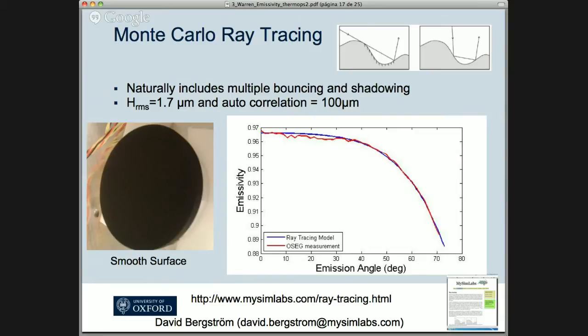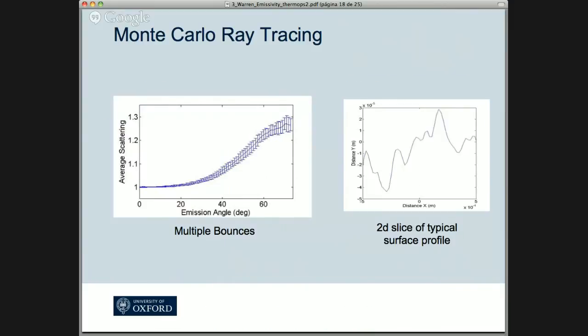So it looks like multiple bouncing becomes important from then onwards. And this graph here is just showing a 2D slice through the typical surface roughness I'm expecting. So you can see the RMS height distribution is of the order of a micron, and the typical distance between 2 features is of the order of 100 microns.